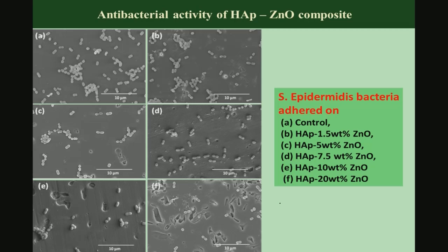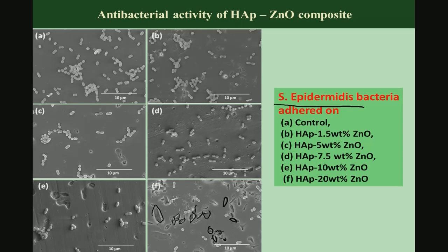Not only Staphylococcus aureus — a pathogenic gram-positive bacterium — but also another gram-positive strain, Staphylococcus epidermidis, showed similar observations. In some places, zinc oxide is visibly leached out, leaving impressions behind, resulting in less bacteria adhering and surviving on the substrate. Occasionally, one or two bacteria are seen, sometimes in the dividing stage undergoing binary fission.